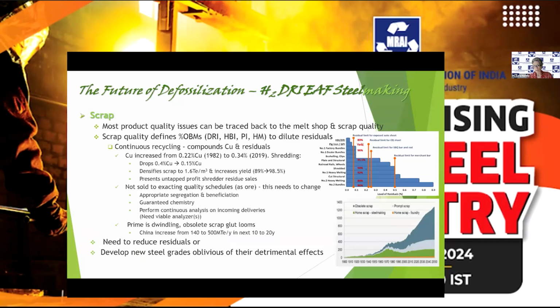The continuous recycling of scrap is going to be a big problem because it's going to increase the copper significantly. We've already seen an increase of 0.12 from 82 to 19. We can shred the scrap to make sure that we remove all the copper coming in from the auto scrap. It also densifies it and cleans it up and gives us a better yield.